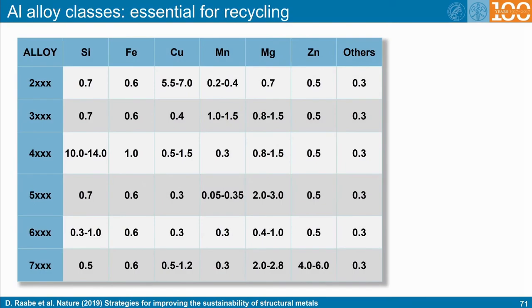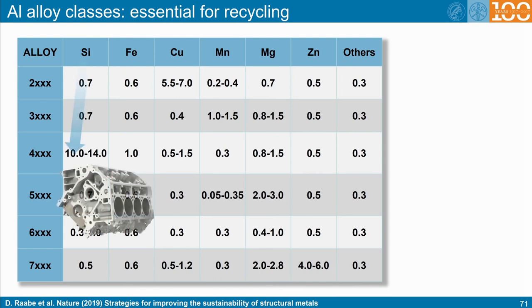This is a rough overview of the many different types of aluminium alloys and their compositional ranges. Details related to the sustainability and recycling of these alloy classes will be the subject of an individual lecture. Here I only give three snapshots of quite different scenarios. A high silicon content of up to 14 weight percent is commonly used for cast products, since the silicon compensates the thermal shrinkage of the aluminium and enhances castability.